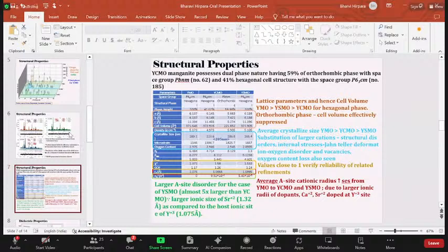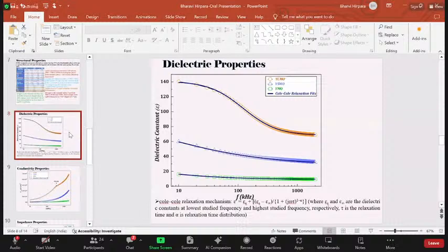Also we can see that at the A site, the disorder created is larger for the case of YSMO, almost 5 times larger than the YCMO, because of the larger ionic size of the strontium ion, that is 1.32 angstrom as compared to 1.05 angstrom in the YCMO side. And we can also take note that for only 10% doping we are seeing so much difference in structural property, which is also the reason for studying YMO for different kinds of applications. Now, going to the dielectric characterization properties of the material.